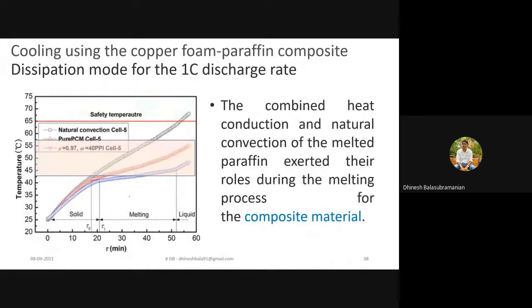And here you can see the phase change material temperature variation. Particularly till 42 degrees Celsius, if you keenly monitor the wax, it would be in the solid form. From 42 degrees Celsius, you need to constantly maintain the same temperature for the next 30 minutes. If you are able to maintain it for 30 minutes, it would be converted from solid to liquid. In the meantime, there would be a huge heat absorption. Till this particular point, both the air and the PCM would be reacting in the same pattern. This black color is the air, this red is PCM, and this is PCM with the metallic foam. Till this temperature, it would be acting linearly. After that, the melting point comes into account. So this is the constant temperature zone, which we have seen in the earlier plot.